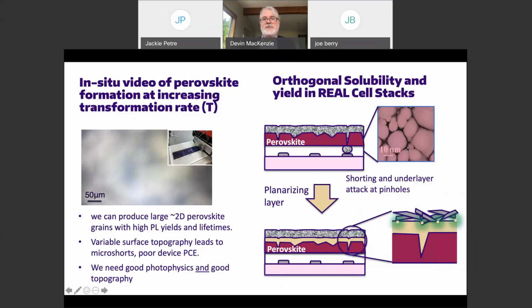If we look at topography in this three-dimensional growth, in the largest grains, a common failure leads to dissolution through pinholes, an attack going through the perovskite and attacking the material underneath the perovskite, leading to a great big hole, or even just real micro shorts in the device, which will sap the device efficiency. So we can't arbitrarily go large in grain size. The holy grail is to go arbitrarily large in grain size, but only purely two-dimensionally. Can we have 100 micron grains that are exactly 300 nanometers thick with nothing bad at the grain boundaries?